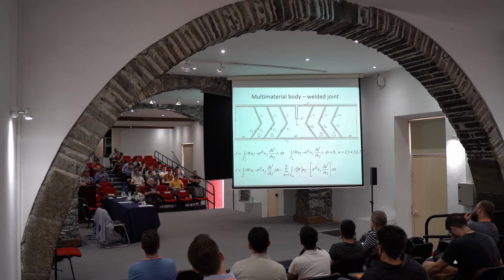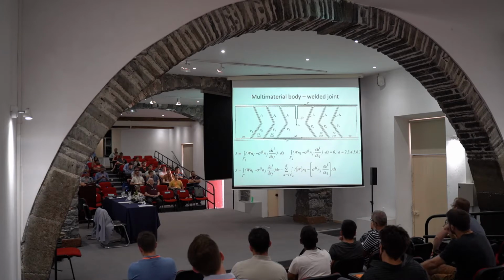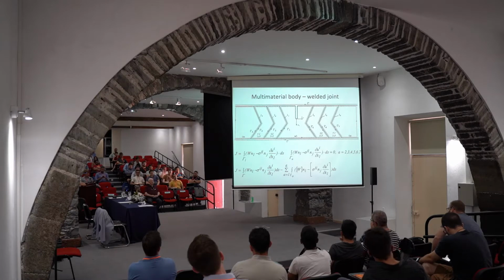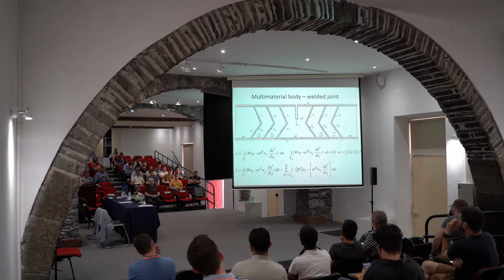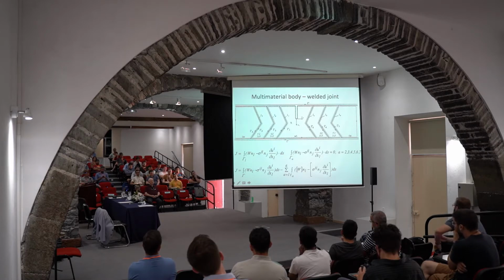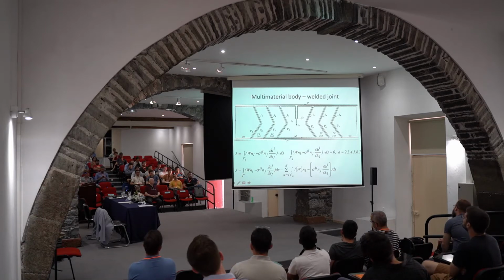if we measure the J integral around the path gamma, which goes all over this specimen, we are crossing different materials. By crossing different materials, we are violating this fundamental assumption, and we are making some kind of error. So let me briefly explain. A welded joint, as presented here, consists of weld metal, at least two different heat affected zones, subzones, that is to say. This one we call coarse grain, and this one we call fine grain heat affected zone, and then of course comes base metal.